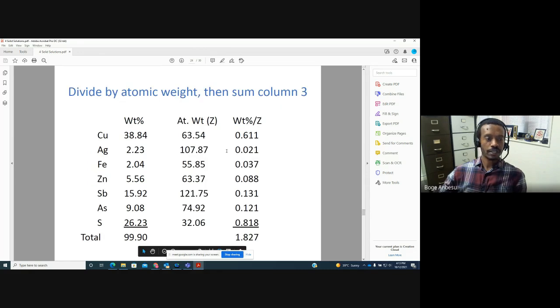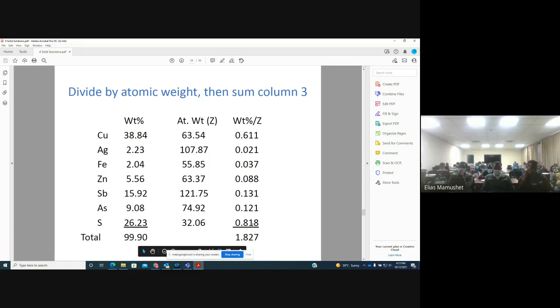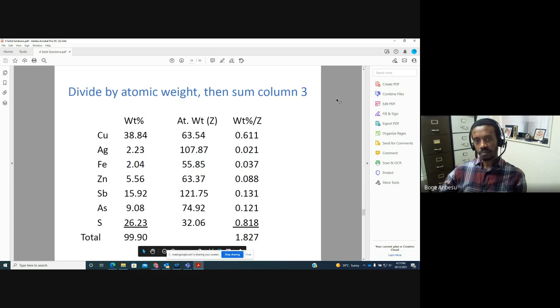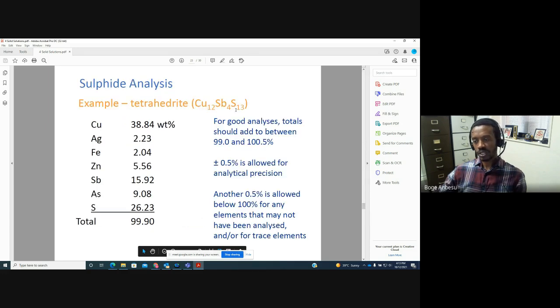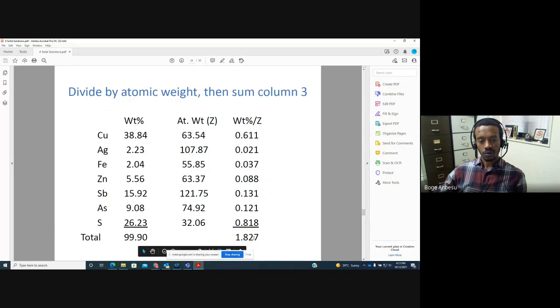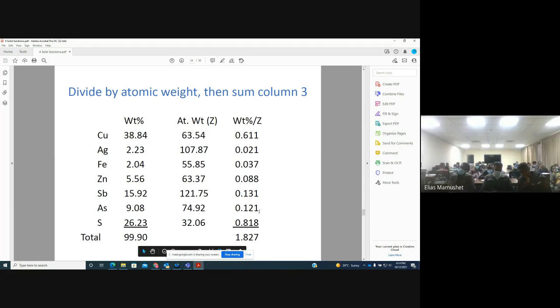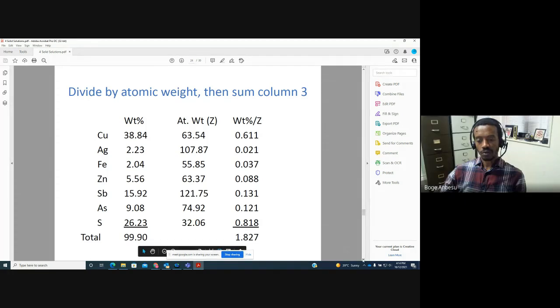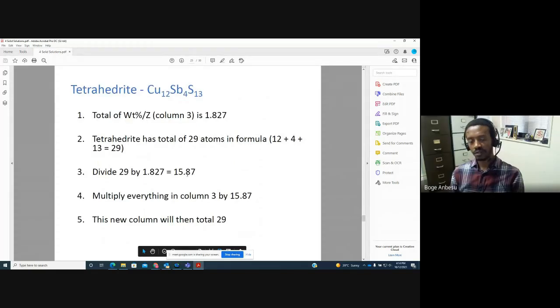Okay, so what I will do then is divide the weight percent by atomic weight for each of them. And then when I do that, I get these proportions. So it's saying all the atoms add up to about 1.8. But I know my atoms should add up to 29 if it's tetrahedrite. So I multiply 1.827 by some factor to get 29, and I multiply each of these by that factor. That factor is 15.87.